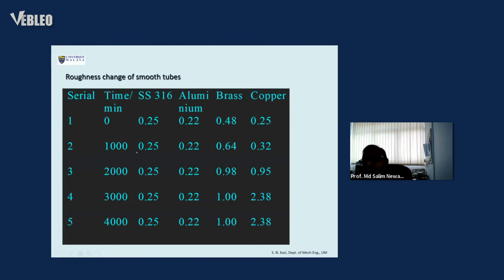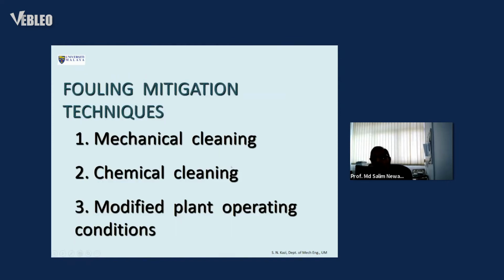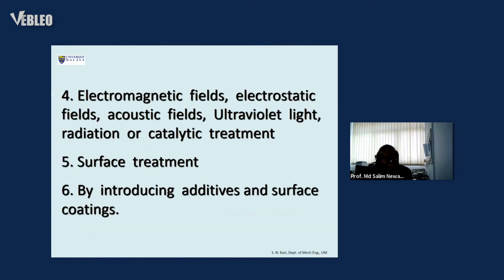And we can see here how the surface changes with the deposition on it. We find there are different ways of mitigation: cleaning, because when it is deposited I have to clean it chemically, and then modifying the plant conditions, electromagnetic fields as surface treatment, and introducing additives and surface coatings. So let's concentrate on the last one.